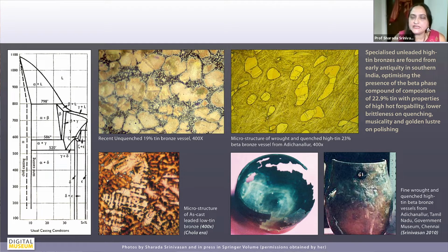And it also seems that this beta phase is actually very plastic. In fact, I've done a study with the late Oleg Sherby, which showed that it is actually quasi-superplastic. So they were able to do very extensive hot forging at high temperatures. And that's why they were able to get these vessels with very, very thin rims. And just to explain to you what would happen if the quenching did not take place, I've put this microstructure at the bottom of a 19% tin bronze vessel, which has not been quenched. And you can see there the formation of this alpha plus delta eutectoid network, which is bluish between the grains. And that is really what embrittles the bronze. And that's why the quenching is very important.